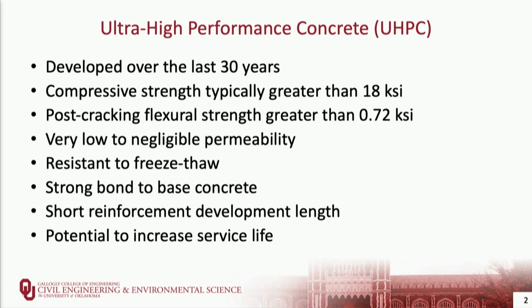So ultra-high performance concrete has been mentioned a couple of times already today. It's a relatively new technology when we talk about concrete, within the last 30 years. It has a very high compressive strength, typically greater than 18,000 PSI. And what really sets it apart, one of the things, is that it has a post-cracking flexural strength. So we're able to get tension strength after we have initial cracking on the order of 700 PSI or more. It has very low to negligible permeability. It's resistant to freeze-thaw. It creates a great bond to base concrete and also has a very short required embedment length for reinforcement that we've already heard about today, to where we can use this as a connection material, repair material, a way to increase the life of our structures.